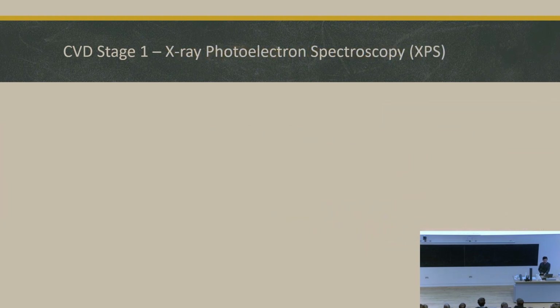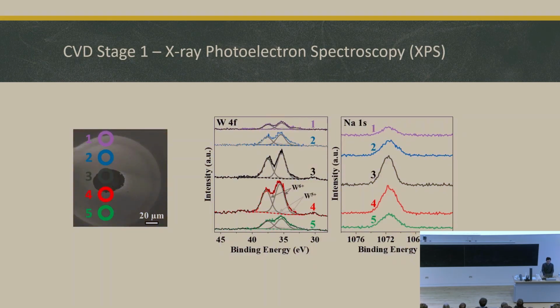So how do we confirm those elements are actually on the surface in the halo? We use another technique called X-ray Photoelectron Spectroscopy. We can shine the X-ray with the 20 micron size on the halo at different spots. We collect the information. If there are tungsten or oxygen or sodium, it gives us some peaks which indicate their presence on the surface. So we can see that from position 1 to 5, the peak intensity is changing, with position 3, which is in the center, having the largest concentration.